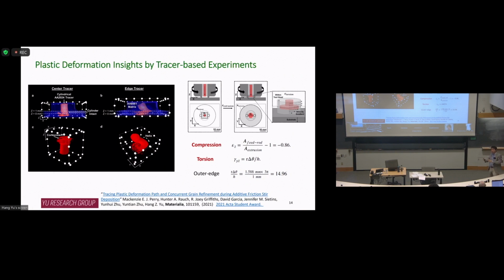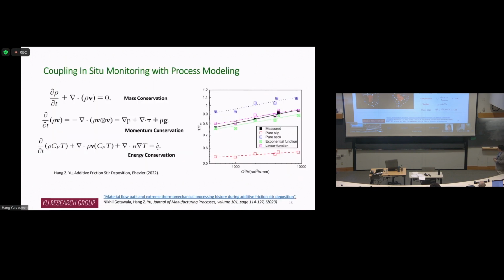And this number is consistent when you do a texture analysis to look at the shear texture of the material. So that's something we can probe from experiments, which is quite limited essentially. We look at thermal from an in-situ perspective. We look at deformation from stop action experiments. We can do more than that by doing some process modeling. Of course, this is not trivial either. But one easy way to model this process is to leverage the framework of computational fluid dynamics. Because the material is going to have extensive flow under the printhead, we can model that as a fluid and get some insights there.